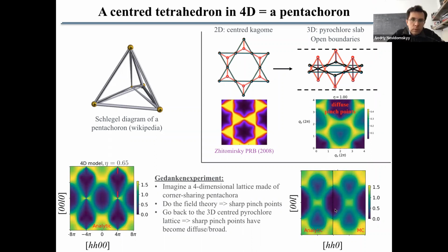I see. So you could basically look at this pyrochlore system as a 3-dimensional cross-section slab of a 4-dimensional lattice. Yes, exactly. The center spin, on the A and B tetrahedra alternately, will be moved along plus t on the fourth dimension and minus t for the neighboring tetrahedron. If you do that, you have really a 3D slab, which is very thin along the fourth dimension. So the Fourier transform is actually on a 4-dimensional space, but you cannot access the fourth dimension because it's a very thin slab, and you don't have enough thickness to access Fourier space there.